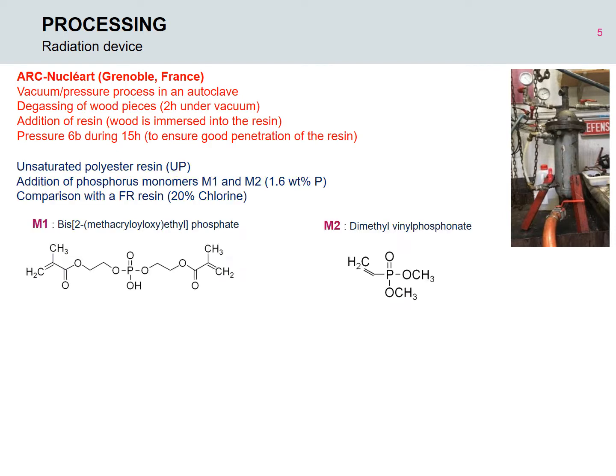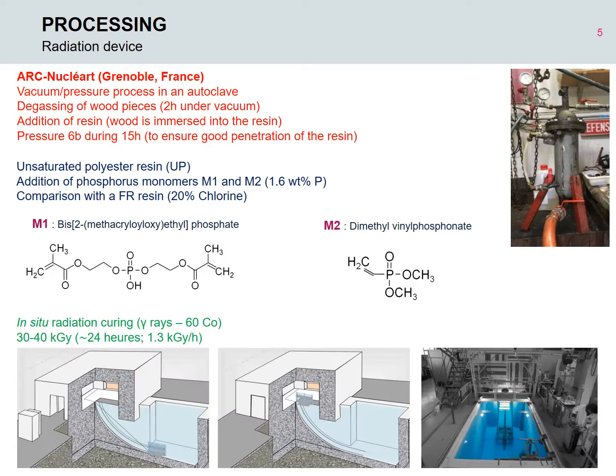of the resin. We have used a typical unsaturated polyester resin, cross-linked with styrene, but we have added phosphorus monomers M1 and M2, and the content of these monomers was adjusted to ensure a phosphorus content equal to 1.6% in the resin. We have also used a commercial flame retarded resin containing 20% of chlorine for comparison. Radiation curing was carried out using gamma rays at a dose equal to 30 to 40 kilograys, and we have checked that the curing is complete at this dose.